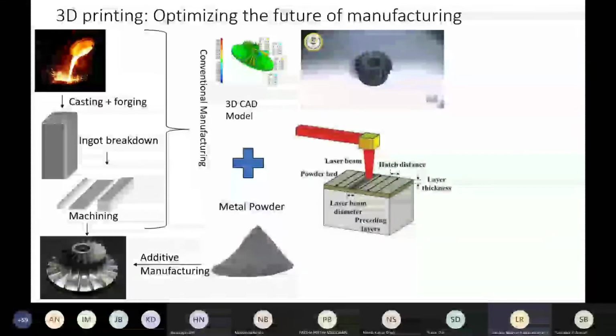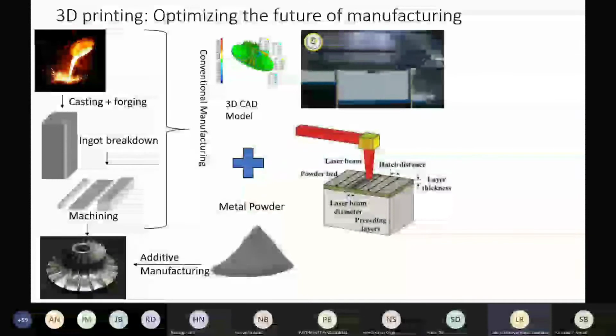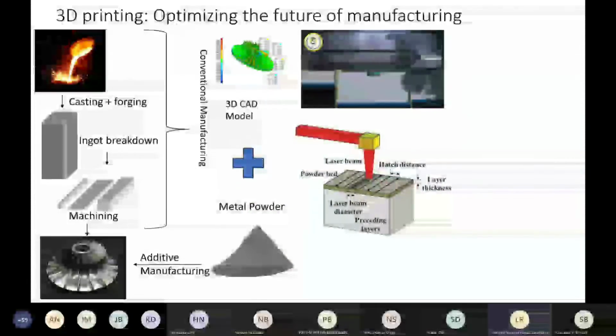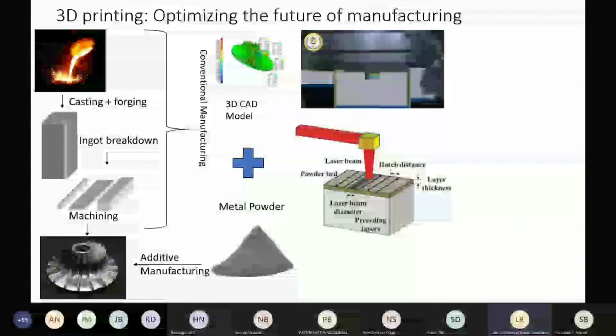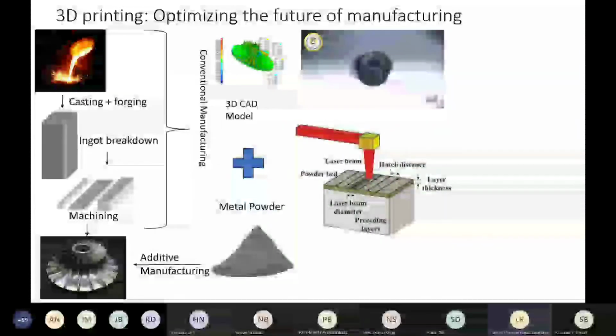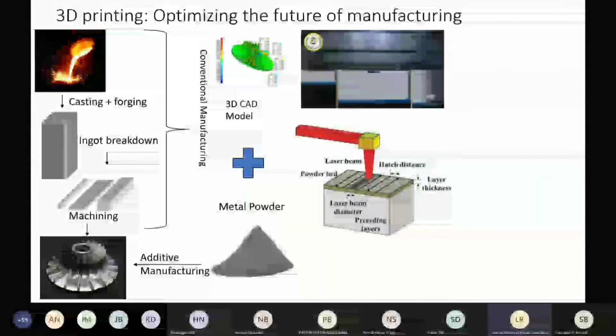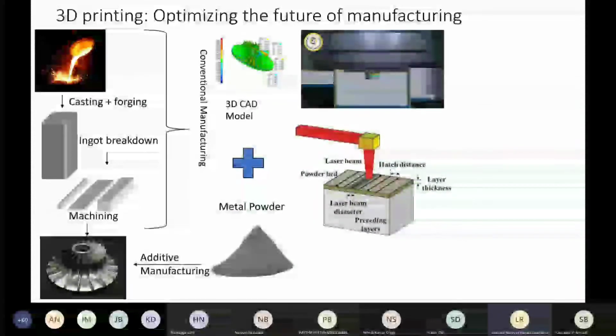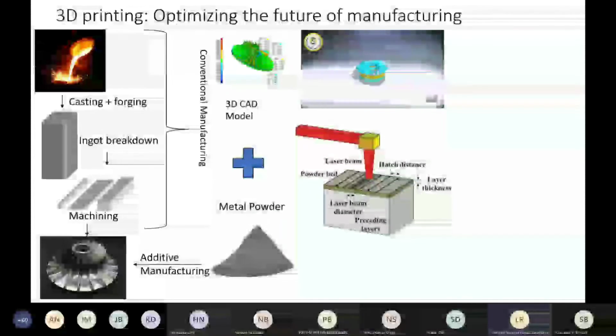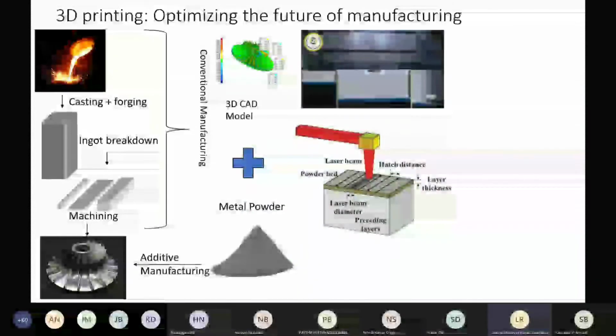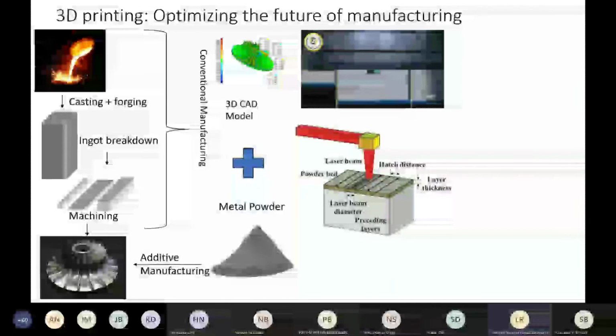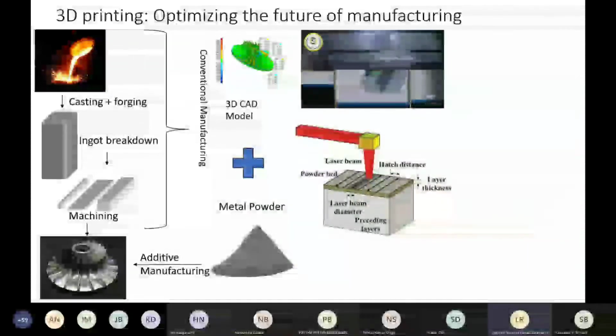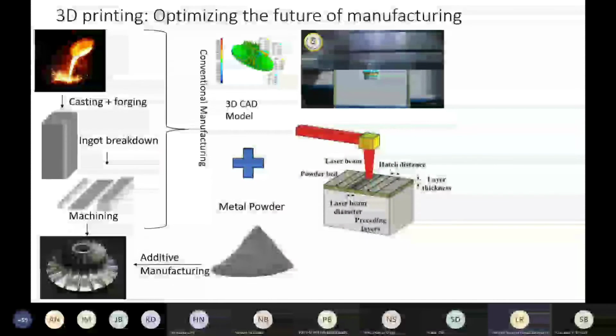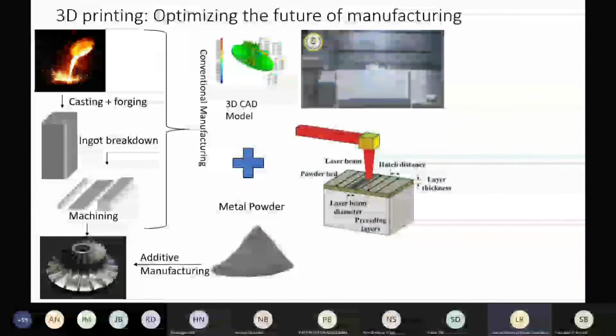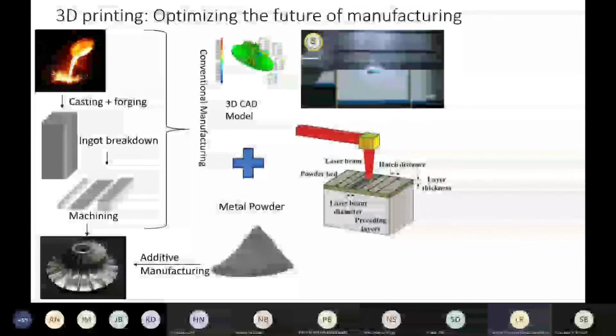And with this, we can also see the kind of process parameters that are coming into play. One is the laser beam or electron beam power. Or you are going to see something known as a hatch distance or hatch spacing. Then the layer thickness, the powder which is going to be printed by this laser beam, again becomes a factor. Then you have a powder bed, and of course, the laser beam diameter. Now the hatch distance and laser beam diameter are slightly different. You can have overlapping laser beams, depending on if you increase or reduce the hatch distance. So these parameters become important.